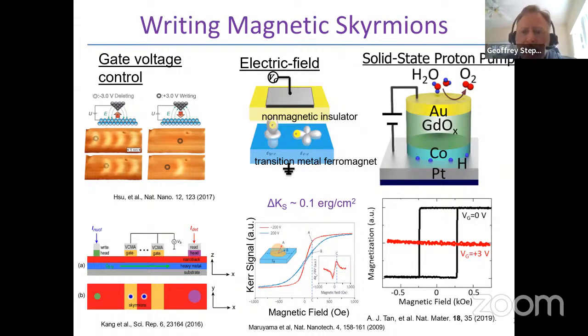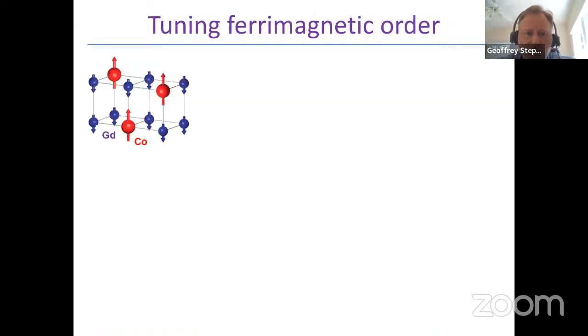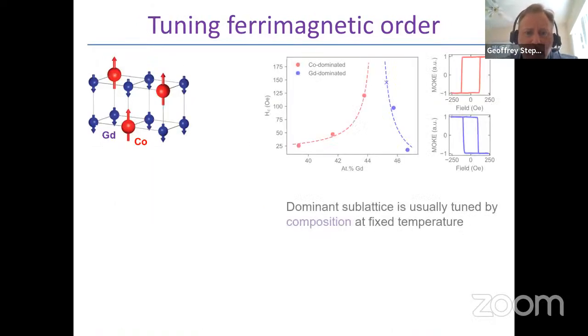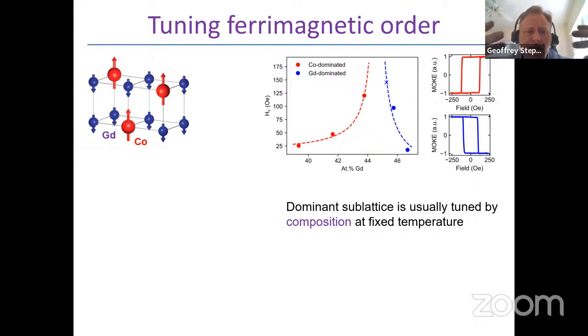And that proton can then be injected as hydrogen into a metallic film beneath it. That allows for a control not only of interface effects, but also bulk effects. And as I'll show you with ferrimagnets, it leads to some really interesting and quite beautiful behavior. So in cobalt gadolinium, there's a compensation behavior because the magnitude of the cobalt and the gadolinium moments are different, but they also have a different temperature dependence.